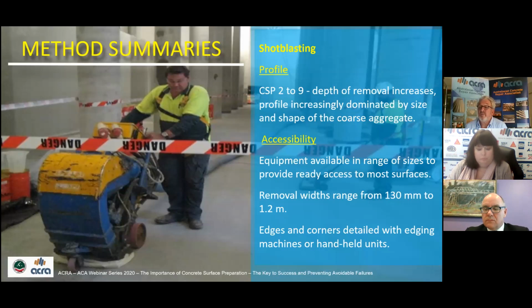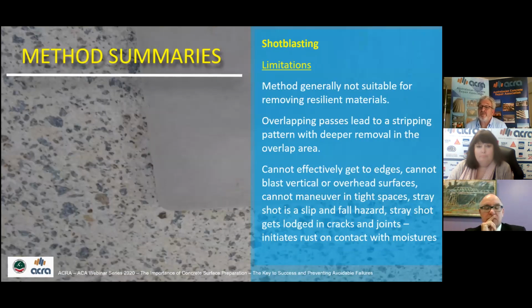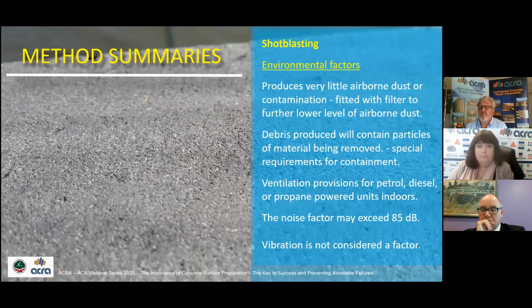Accessibility, shot blasting equipment is available in a range of sizes to access most surfaces. Removal widths range from 130 mm to 1.2 metres. Edges and corners can be detailed within 6 millimetres of vertical surfaces. Limitations, generally not suitable for removing resilient materials. Overlapping passes lead to a striping pattern, which means there's deeper removal on the overlap area. Cannot effectively get to edges. Can't manoeuvre in tight spaces. Environmental factors, they produce very little dust.